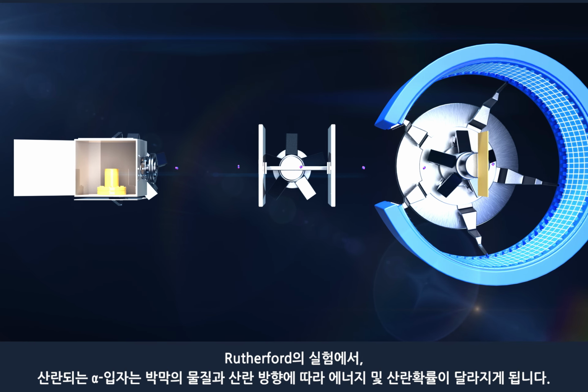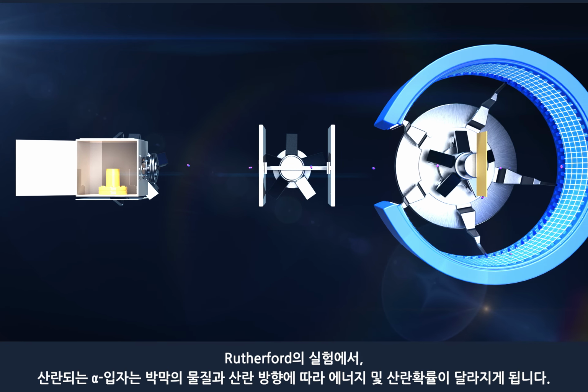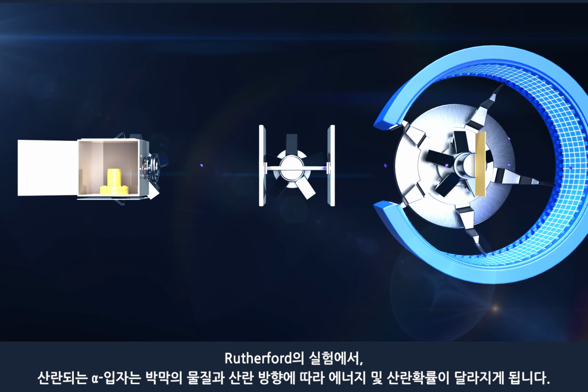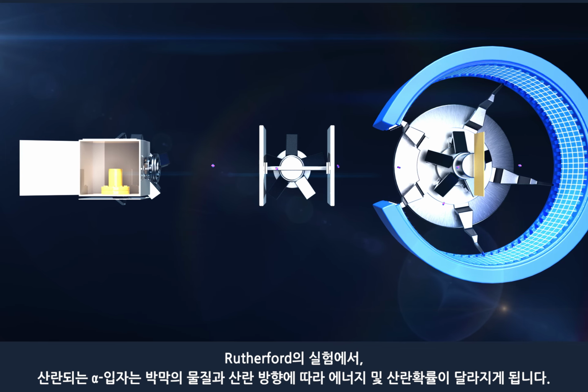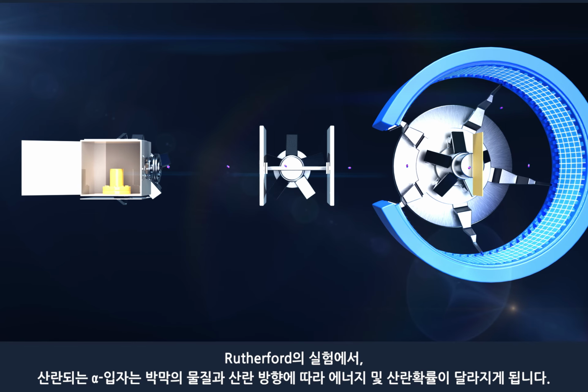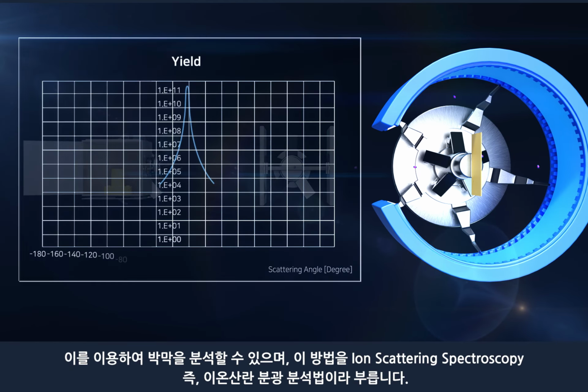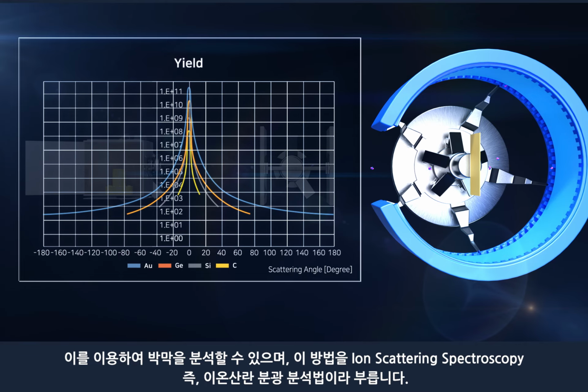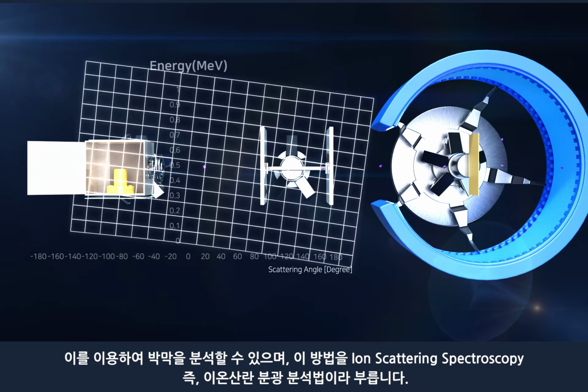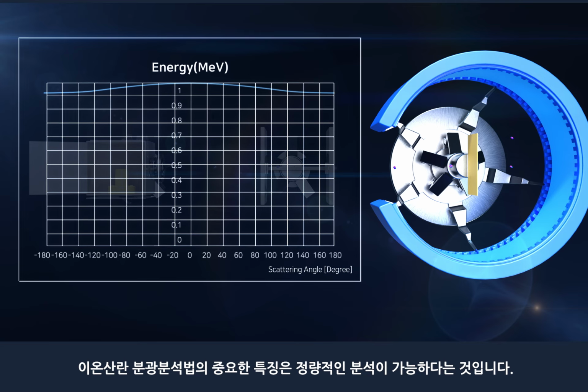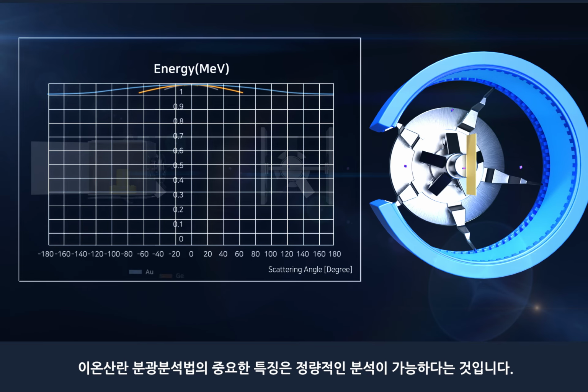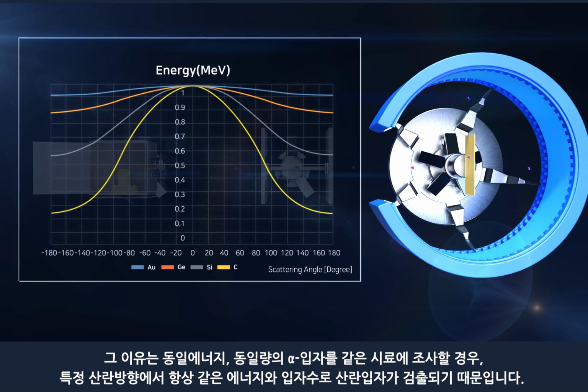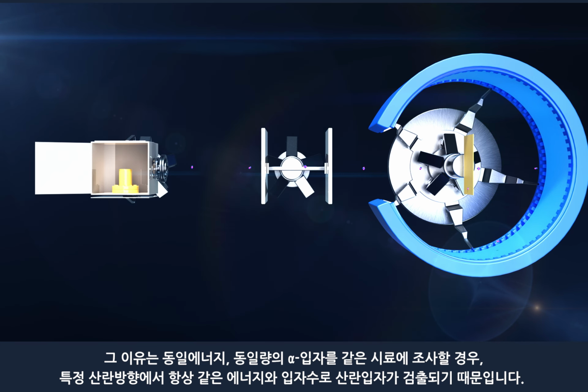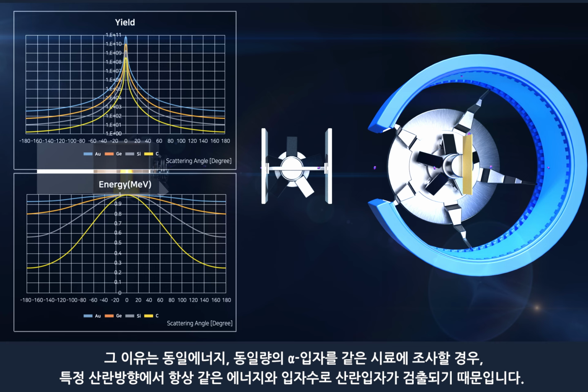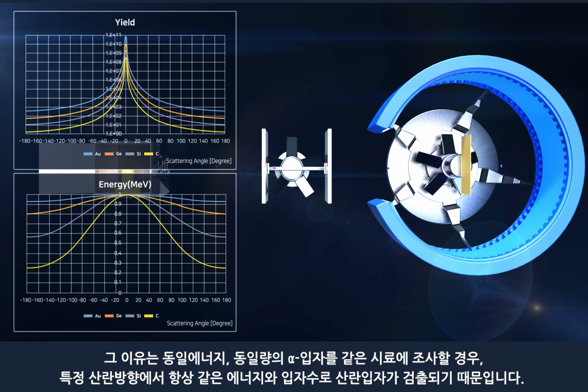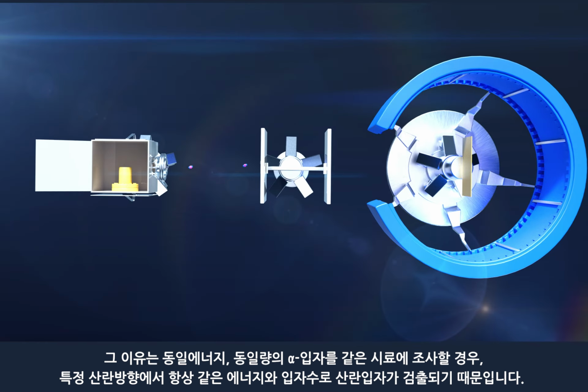According to Rutherford's experiment, alpha particles that scattered after collision have different energies and scattering yields depending on the material of the thin film and the direction of scattering. Thin films can be analyzed using ion scattering spectroscopy. The greatest advantage of this method is its quantitative analysis. This is because scattered particles are always detected at the same energy and yield in a specific scattering direction when irradiating alpha particles of the same energy and amount.